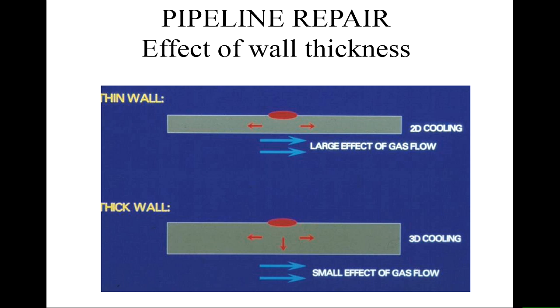If you have a much thicker wall pipe, then you get three-dimensional conduction of heat. Some heat is conducted directly towards the wall, others goes along the length of the pipe. And under such circumstances, you don't get such a large area of hot pipe wall in contact with the gas, which means you get a lot smaller effect of the gas flow on the cooling rate. But you can have quite a big effect of the pipe thermal mass. So generally, when we're welding on a gas pipeline and we're worried about flowing gas inside it, it's only if the pipe wall thickness is low that we really have to factor in the gas flow into any of our calculations.